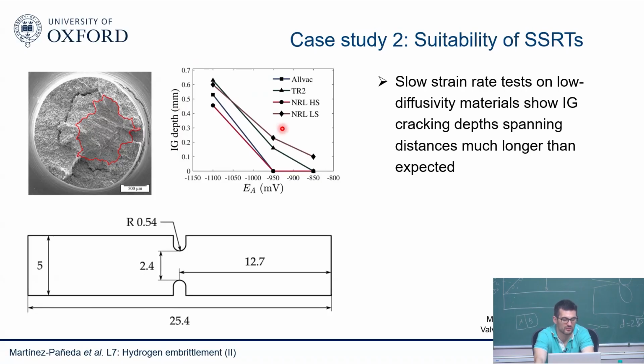One hypothesis that they wanted to test with our models is that hydrogen is not a failure process where you just pull and at some point failure happens, which is what people thought. Maybe you get a crack initiating, the crack grows slowly and carries the hydrogen with it, right? But if that happens, that will make this kind of test non-suitable, because then it's kind of a fracture test. You have a crack, it's a completely different story. You need some crack measurements. Do you have measures of crack initiation, crack growth? What do you care about? Failure? So that would make the test unsuitable. So this was their hypothesis. So we wanted to test this.